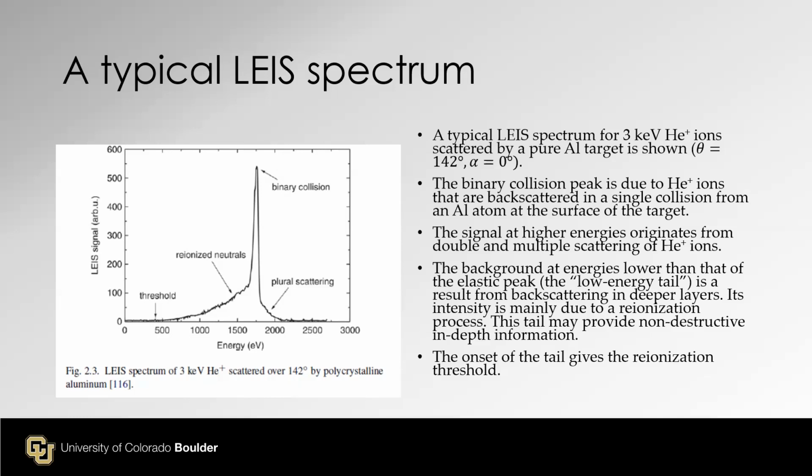And this binary collision probability is not super high, so we have to have a lot of surface atoms to see this one. Okay. Got it. So it's very different. The smallest spot size possible is 10 micrometers, but in practice, we use a millimeter by millimeter area to get the spectrum. It's the same for XPS.